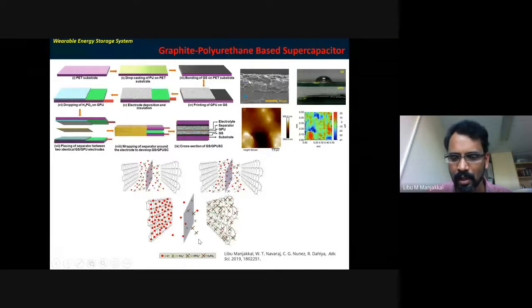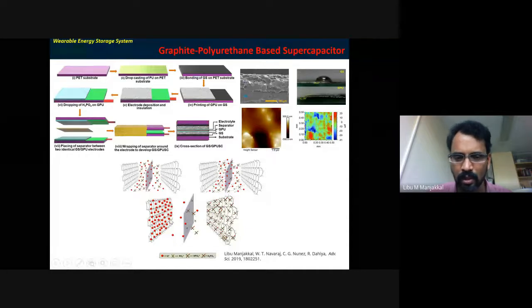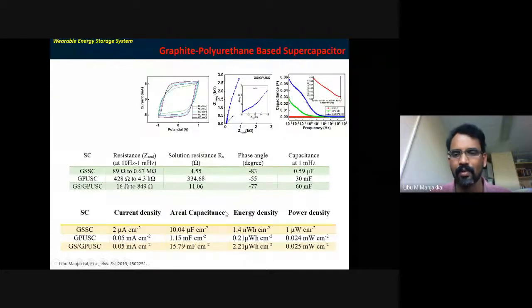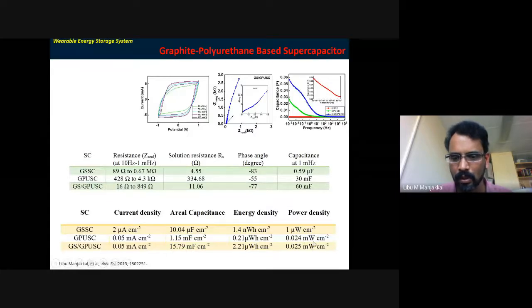And again I used phosphoric acid here. When I applied the electrode, the phosphoric acid contains many positive and negative ions. These are attracted towards the graphene sheet. And here, when I compare the devices, the graphite polyurethane based supercapacitor, I'm not giving you a detailed explanation, shows a better performance in terms of capacitance, and also high energy density as compared to the normal supercapacitor. You can see here the device operating in a milliwatt range.